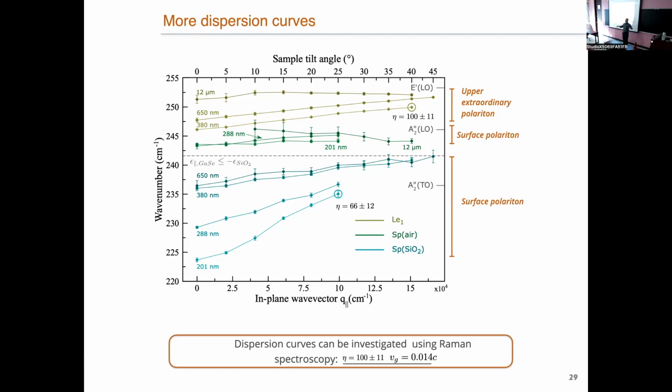The wavelength of the phonon polariton is about 40 micron. So whenever you have a sample that's thinner than that, you are in a regime where you could achieve some confinement. But naturally, confinement you get only if you have coherence length, because to form a standing wave, you need coherence over at least the thickness. The coherence length of phonons is very small.